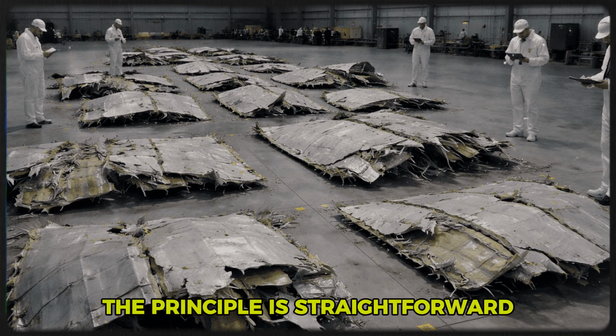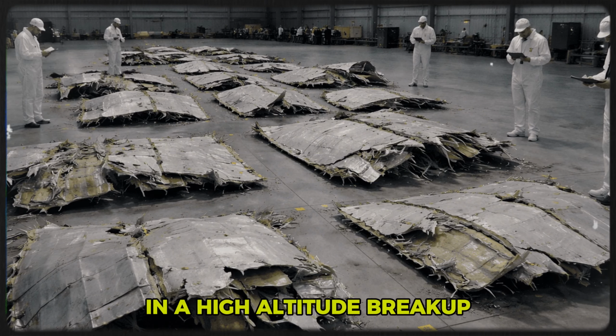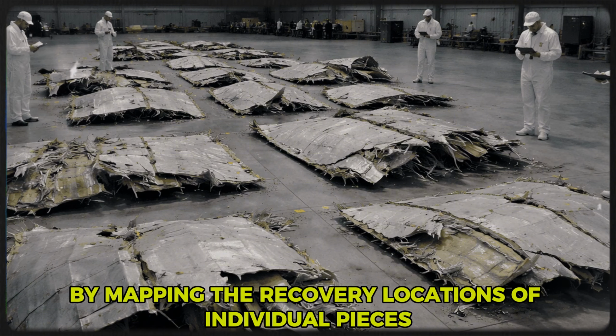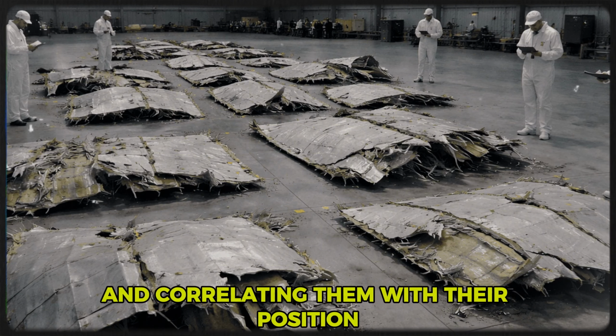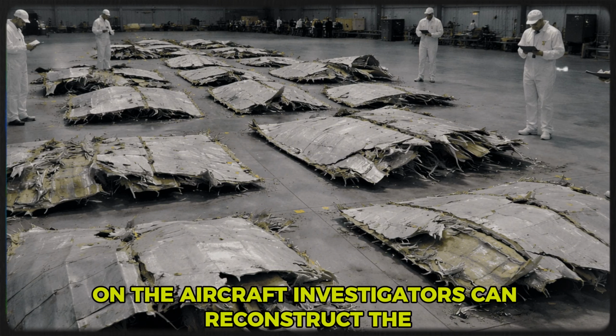The principle is straightforward in a high-altitude breakup. The pieces that separate first travel the farthest from the main debris field because they are released at the highest altitude and have the longest fall time, during which upper-level winds carry them laterally. By mapping the recovery locations of individual pieces and correlating them with their position on the aircraft, investigators can reconstruct the sequence of disintegration. For Flight 611, this analysis determined that the aft section of the fuselage had separated first.